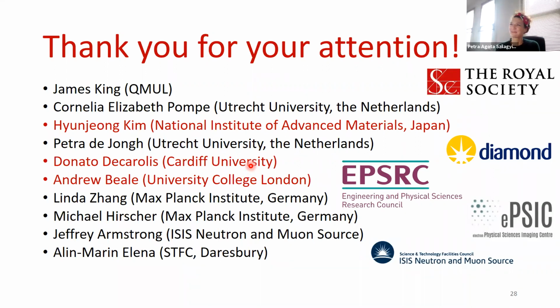I think that's actually the beauty of these frameworks, that it's probably not. So we do see that we significantly change, particularly, the surface electron density in these frameworks. I didn't show all the samples we've made, but we are quite keen on looking at functional group effects. And depending on what group you add, you can really have huge surface oxidation, partial surface oxidation effects on the catalyst. So there is a huge change, and if the performance of your catalyst would depend on the promotion effects, then it would be very different. The catalyst performance for the catalyst embedded in the frameworks would be very different from the naked freestanding ones. Excellent.